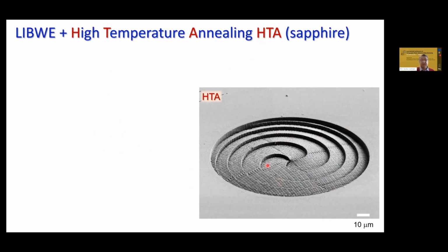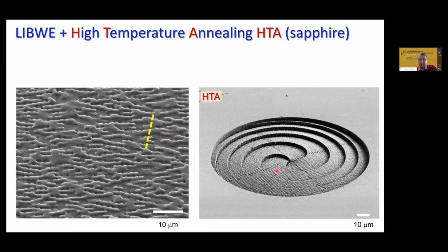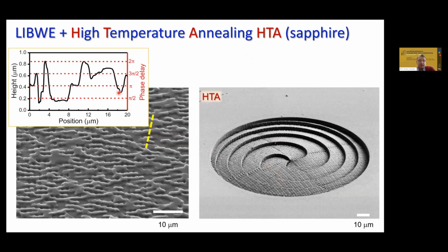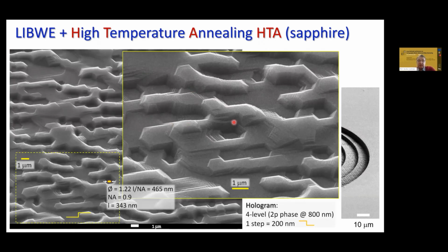Here it's optical vortex generation, and here is a diffractive optical element, which is defined by 4 levels to cover 2 pi phase, and all steps are ablated, and then after high temperature annealing, they are not disappearing. They actually are made much cleaner and much more defined. And you can also recognize that the surface reconstructed by this high temperature annealing into a crystalline surface. You can recognize the C-plane on the surface of sapphire, which was used to ablate those diffractive optical elements. So certainly they will have some scattering because of the crystalline nature, but they don't suffer from the problems of debris, which is very usual for laser ablation.